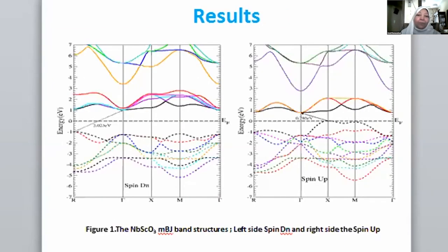Now, for the band structure that we are seeing here, I didn't put in the GGA. I've done both the GGA, or generalized gradient approximation, as well as the MBJ. But what I can just say here is that when I used the MBJ, I found that the band gap opened up, and instead of being a half metal as it was with the GGA, it became a metallic semiconductor, but of course in both the spin up and the spin down.